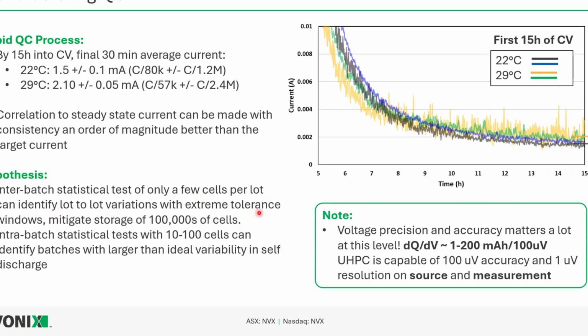So these inter- and intra-batch statistics with only maybe a few cells per lot could identify lot-to-lot variations with very extreme tolerances, to be able to identify, hey, this super sack of cathode, when you look through all the metadata connected in Voltaiq, like Kevin showed, was linked to this batch having a slightly higher self-discharge rate, with very high confidence just in 15 hours of testing. Or even within one batch, doing a statistical test with a relevant number of cells, tens to 100 cells, to show what that band actually looks like, and is that band acceptable in only a very short time.